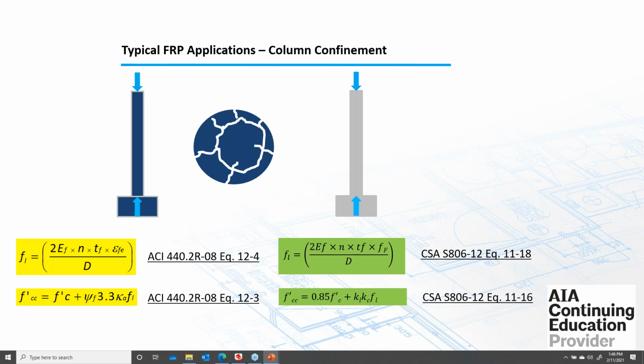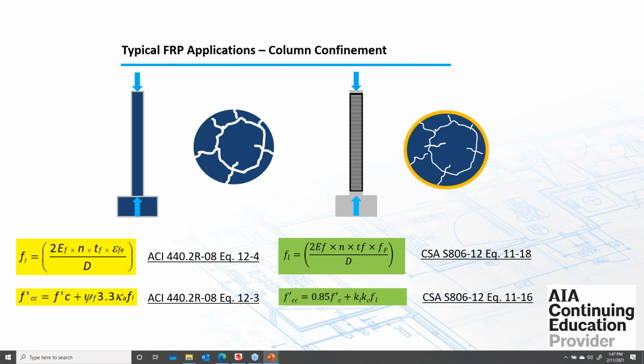So if you're looking to, say, triple the capacity, you're adding a ton of weight, and you're probably not going to get there with FRP. The difference with columns versus flexural or shear is that it is not what we call bond critical, so there is no delamination concern. You can actually use 100 or 200 layers of FRP. In theory, you could get any load you wanted, but it's going to be way too expensive when you start talking about that many layers. So while you can get some increase, it's not the best way of adding compressive capacity to the column. There are certainly other ways that'll get you more. It's really that ductility enhancement that we get out of the FRP.